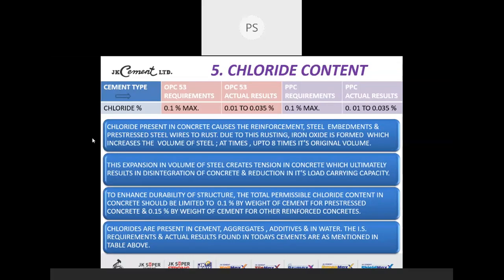Now, it is very important for a quality control engineer to control the chloride content, especially in the cement as well as the additives or admixtures that we are adding. In India, we normally add naphthalene based or PC based admixtures, and they also have a considerable amount of chloride content in them. A quality control engineer should buy such admixtures from a reliable brand and ensure that the chloride content is mentioned in the test report and is within the permissible limit. Next, please.